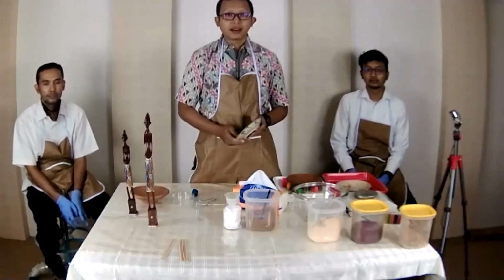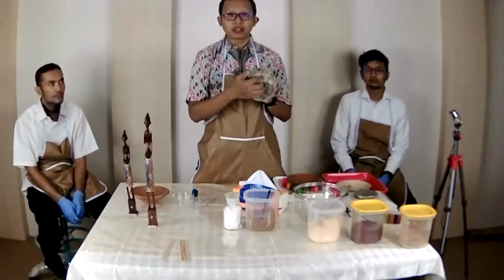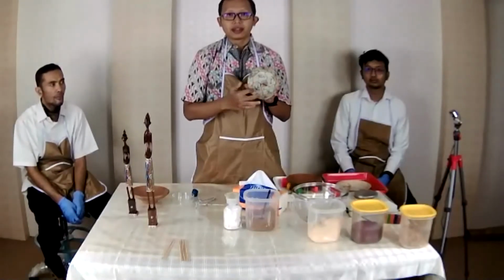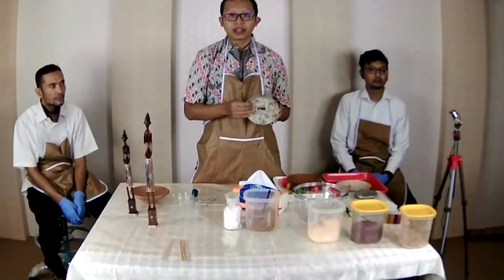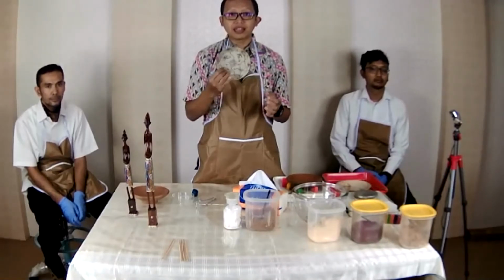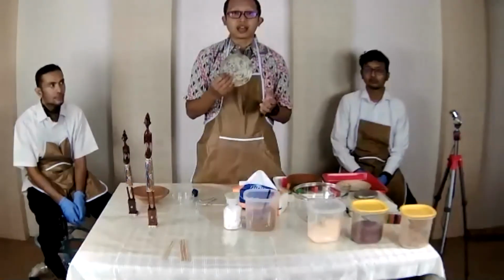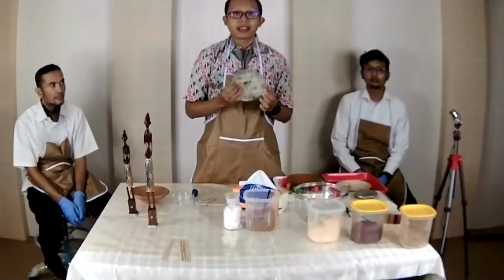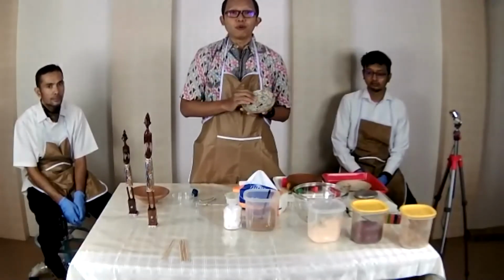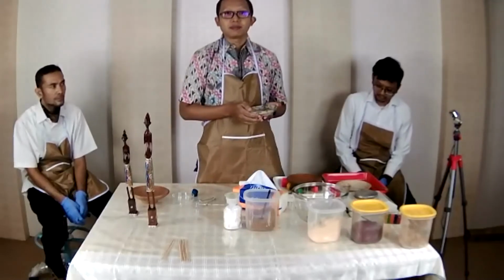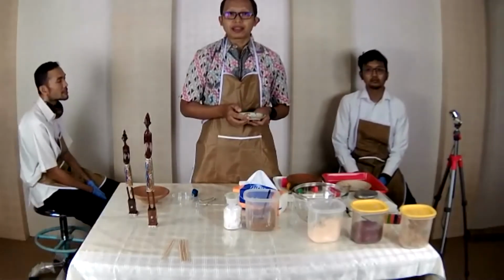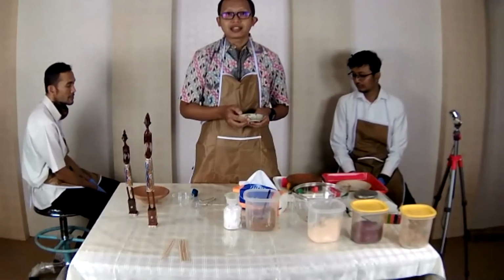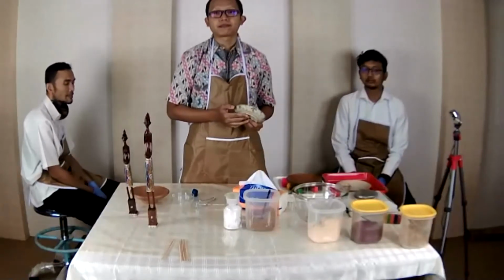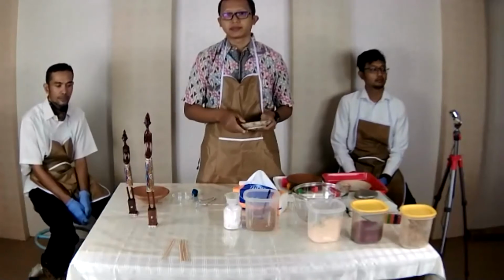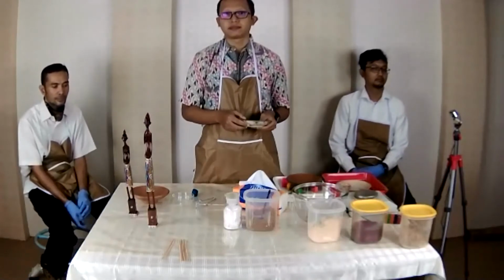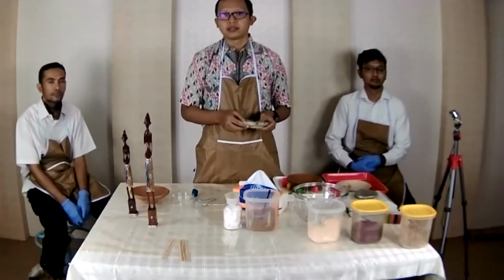From our experience, if you apply this in accordance with the procedure, as you can see in this ceramic sample, it's broken into several fragments. We did this with the anchor 8 years ago, and you can see that it's still intact at the parts that we joined. So if it's loose or detached, there must be an error in the attaching process and the procedure when you repair it.